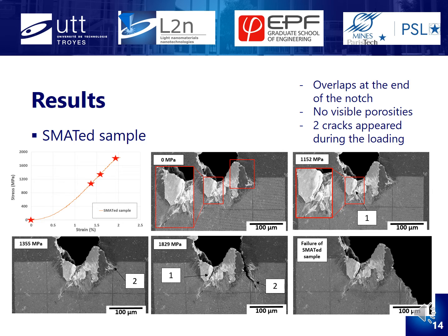For the SMAT-ted sample, what is particular is the material aggregation around the end of the notch, due to the mechanical treatment. These overlaps are evidenced in red rectangles at the initial state, and interestingly, the two cracks presented appear in this location. The first crack at 1152 MPa is in the overlap on the left, and compared to the as-fabricated sample, the treatment delayed the initiation of the crack. However, the sudden propagation of crack number 2 at 1829 MPa leads to the failure of the sample, but there are no visible porosities at the surface to determine if they have an influence. Instead, the overlap may have created a stress concentration at the intersection, increasing the probability of crack formation at the surface. The behavior of the cracks during loading leads to the conclusion that it may be possible to predict the location of cracks by observing the overlaps; however, other tests should be conducted to validate this assumption.